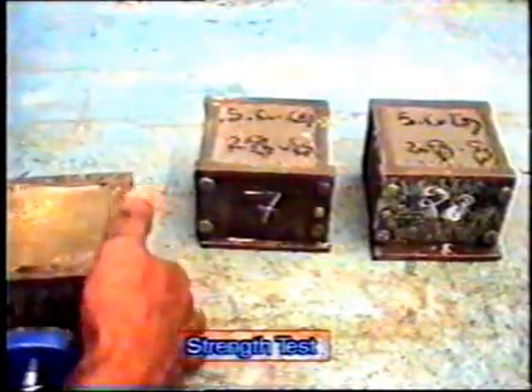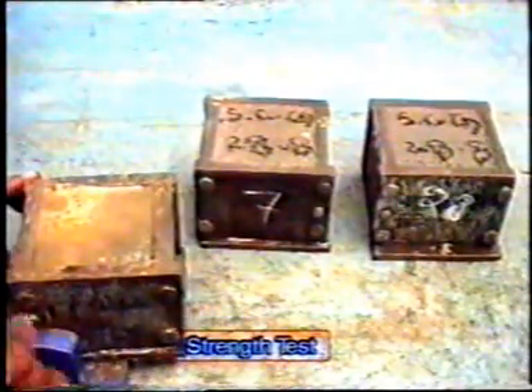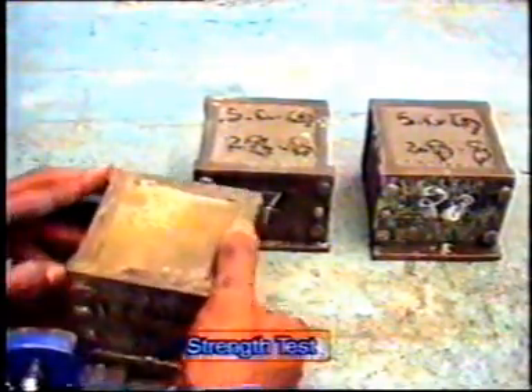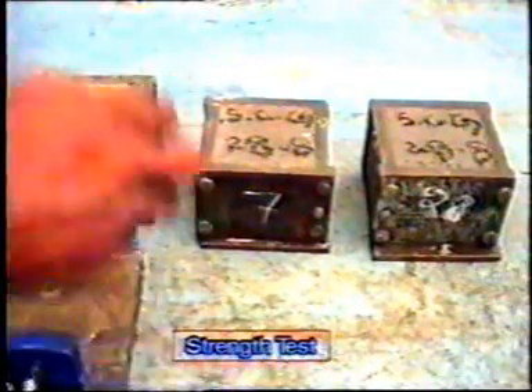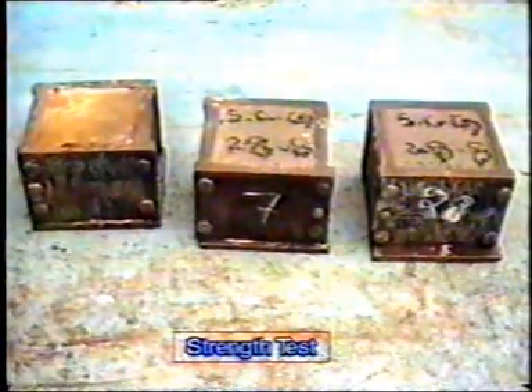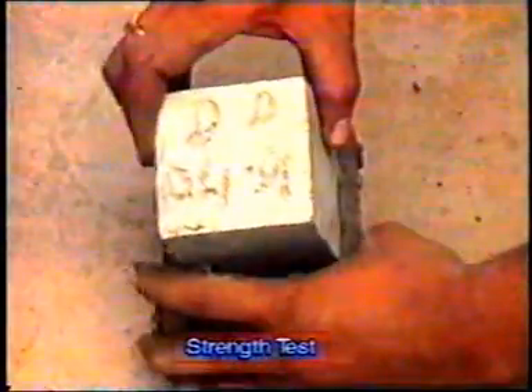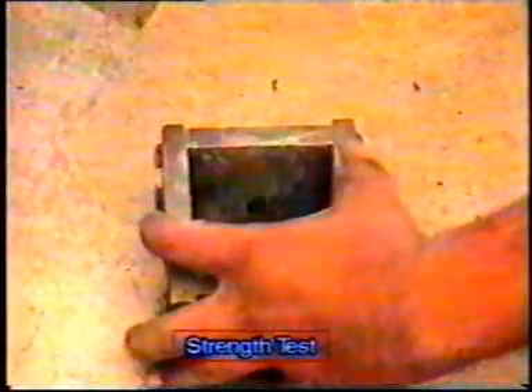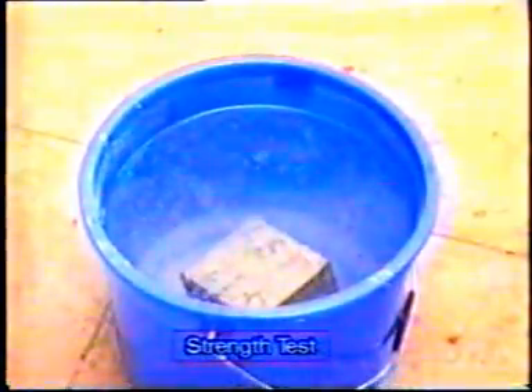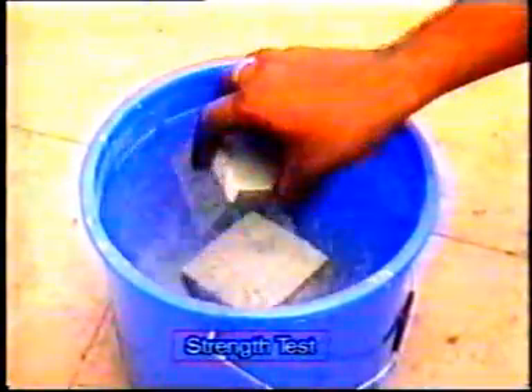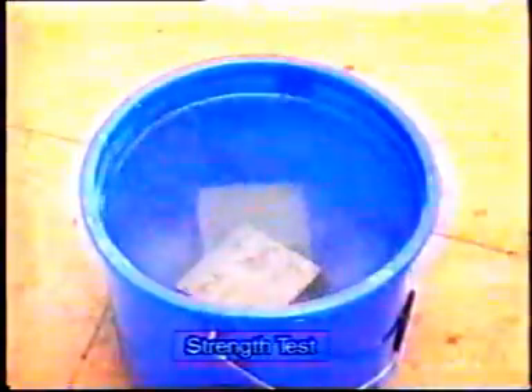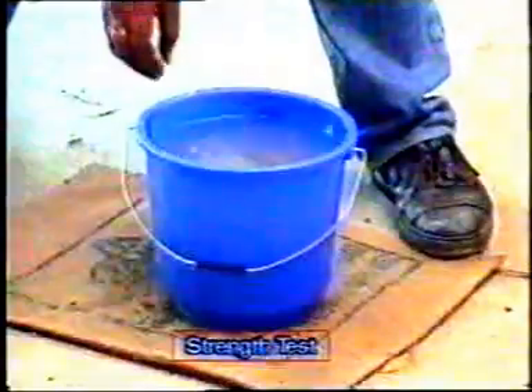Keep it in the room temperature for 24 hours. Then remove it from the mold. Keep it in water curing for 27 days. Three such molds are prepared. One is for 3 days testing. Second is for 7 days testing. And the third one is for 28 days testing.